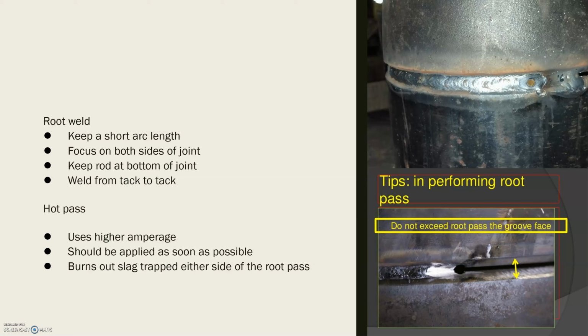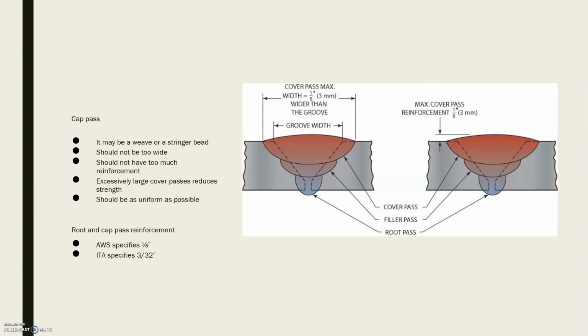The hot pass is done to lock in the root pass by cleaning and fusing the toes of the welds. It's best practice to weld the root and hot pass without leaving it too long. If you leave it too long, there is a time where you could possibly get shrinkage cracking. The rest of the joint is pretty much the icing on the cake. Make sure it's clean. Wide weaves increase the heat affected zone, which can reduce the strength and make the material brittle.